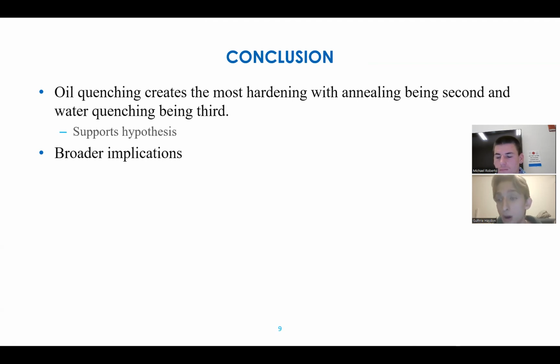And as I mentioned, there are broader implications because we realize that when we quench something, we are altering the alignment of the chemistry. This can make it either harder or softer in terms of the Rockwell readings and Brinell. And so again, this is super important because we can optimize certain material properties and use it to our advantage, and from a production standpoint, having products that we can cheaply anneal or quench can be great in terms of minimizing the weight or the cost and manufacturing more of them. So overall, this has a lot of broad implications that maybe we don't see straightforwardly.